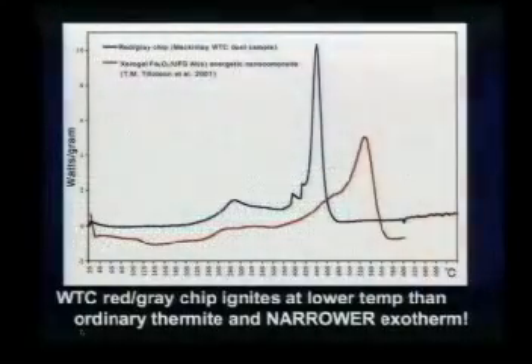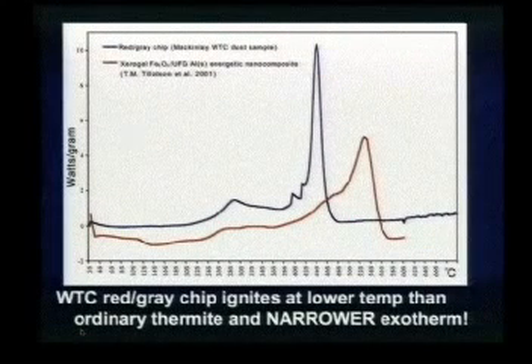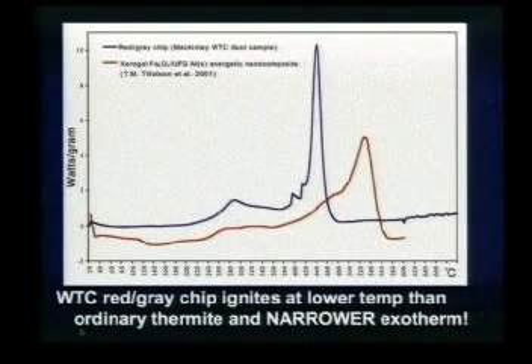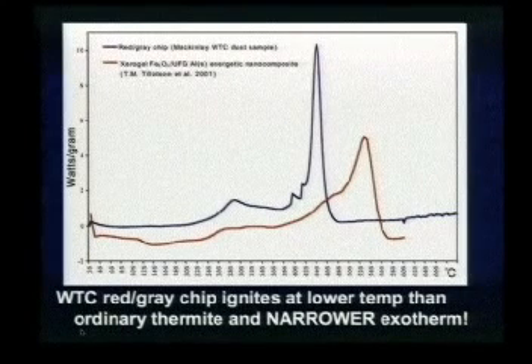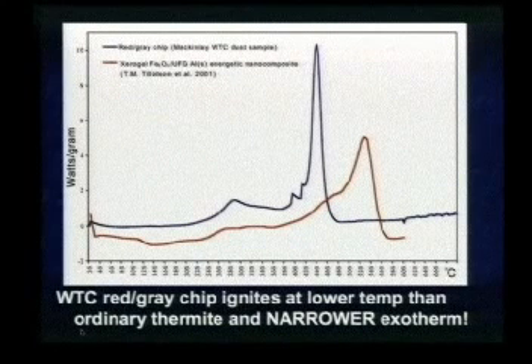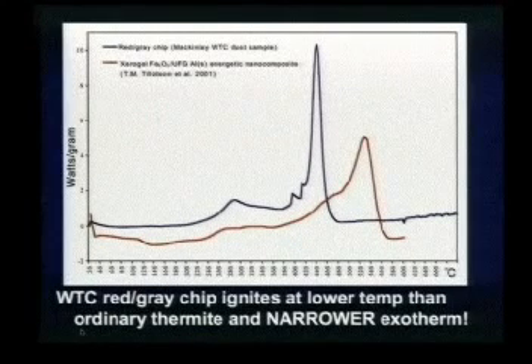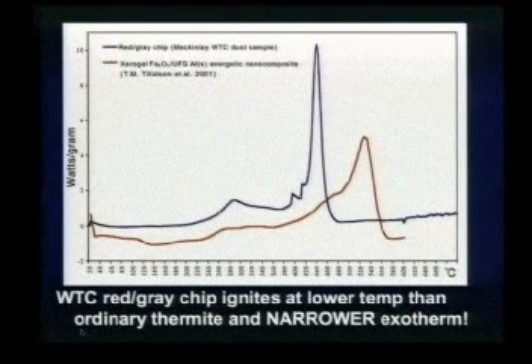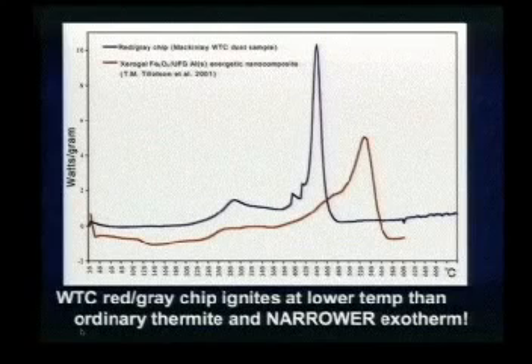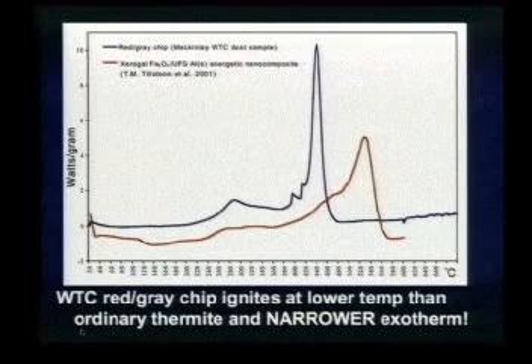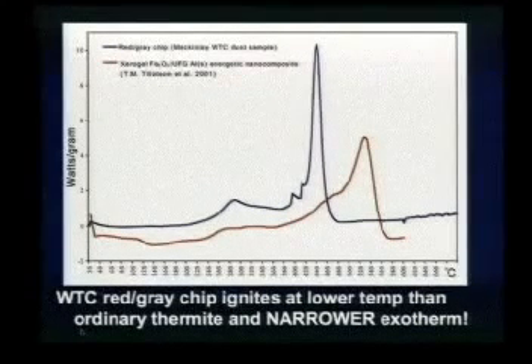The red chip, from the red material from the World Trade Center dust, I can't remember. Yes, it says McKinley. This is a McKinley sample, Jeanette. And look at that, very narrow, and it goes off at about 430 centigrade, a little lower in temperature. The finer the material in general, the lower the temperature at which it ignites. The narrower the peak, the more explosive, you see, the faster the energy release.